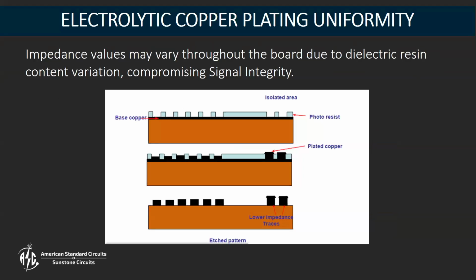All right, so electroplating. Here's an example of electroplating and how different designs can impact signal integrity. We use a photoresist as our plating mask, and we plate in the channels of the photoresist, and those will become your functional copper features, your traces, your pads, through holes, etc. If the copper isn't evenly distributed, or we have areas of what we call high current density because of the amount of copper in an area, we can get variations in height of that copper.